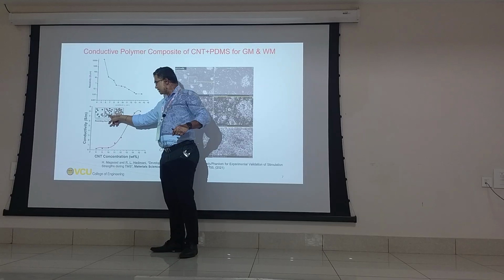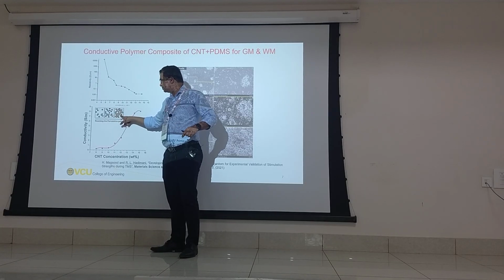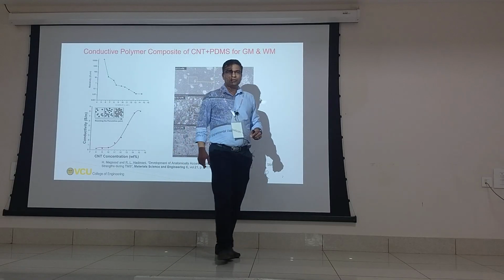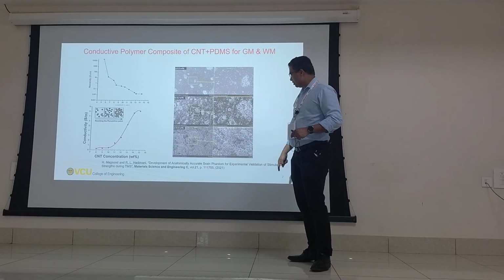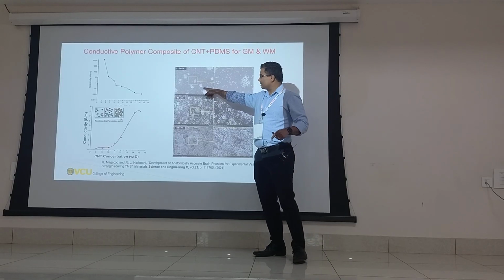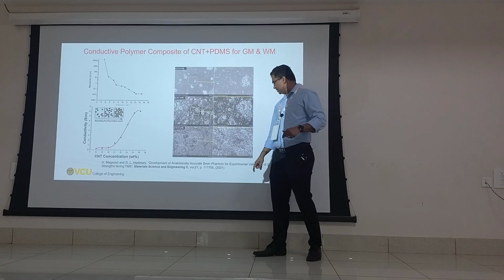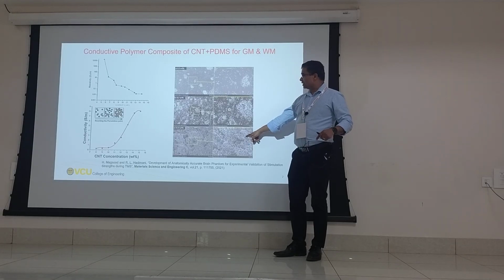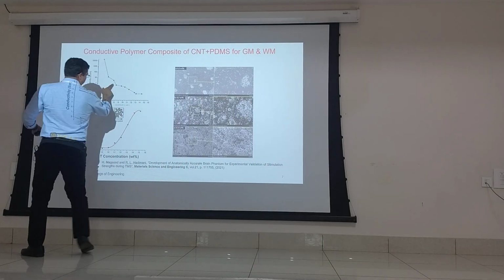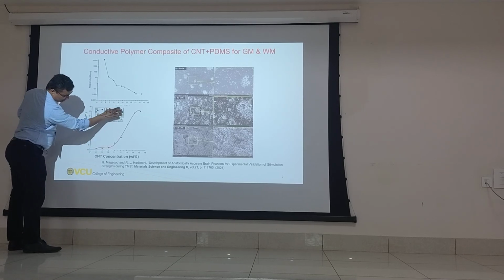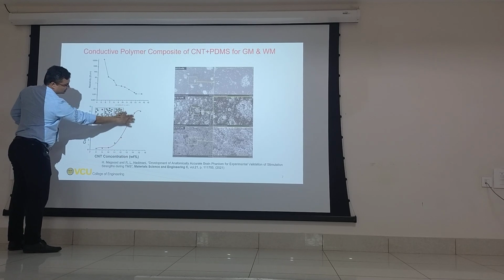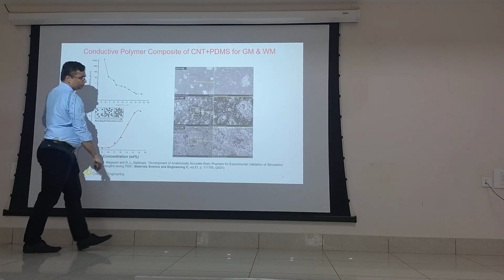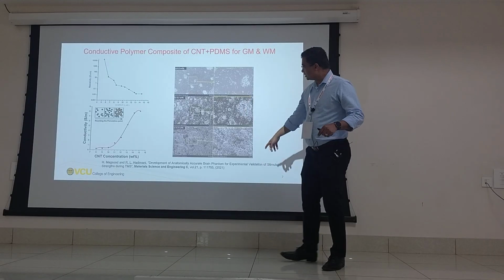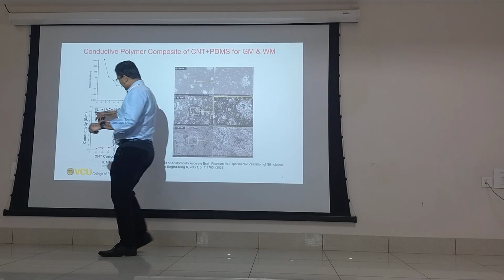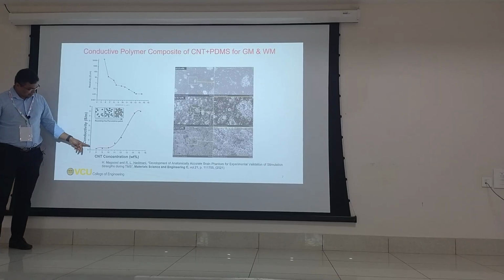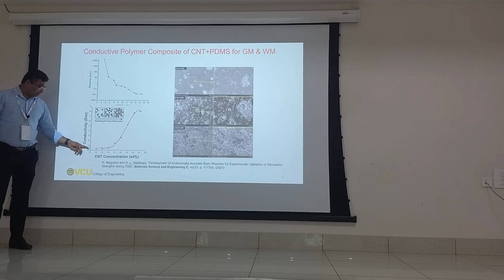That is called percolation point. You see here, here and here the conductivity is not that high, but as soon as it gets a continuous path from one point to another point, the conductivity shoots up. And this is 5.3% carbon nanotubes, 8.3%, 14%. You see the network here? It's already high. So 14% is already over here somewhere. Here the network is already formed. Okay? So that's a fully connected network. But we don't need that much because our conductivity is not 8 Siemens per meter. We need somewhere around here. Right? We have small conductivity.